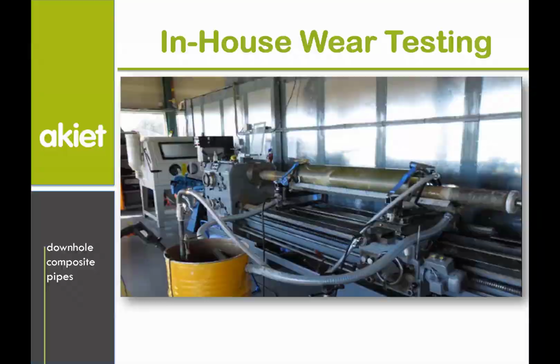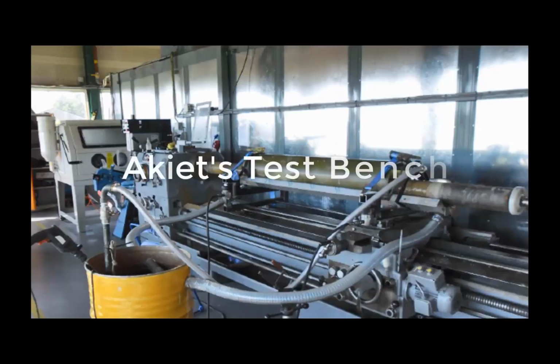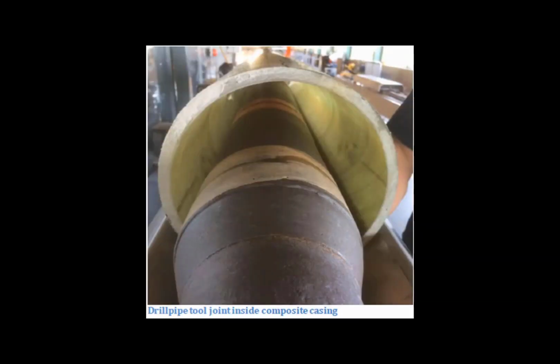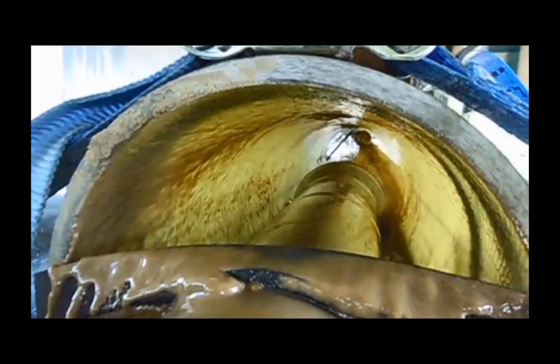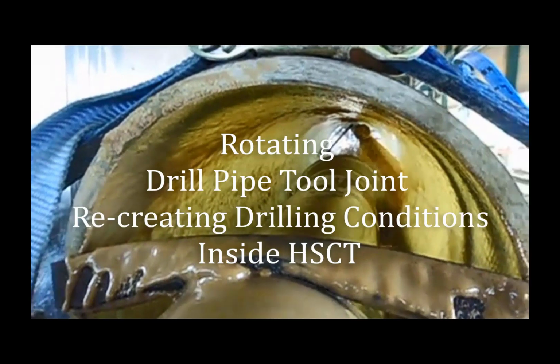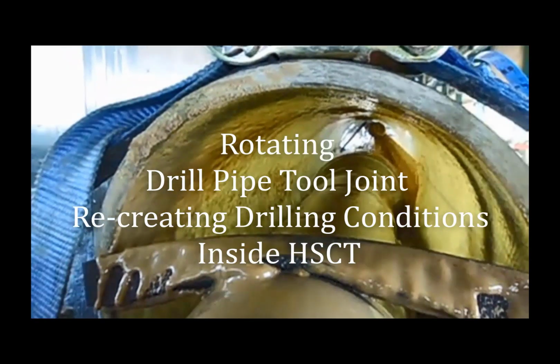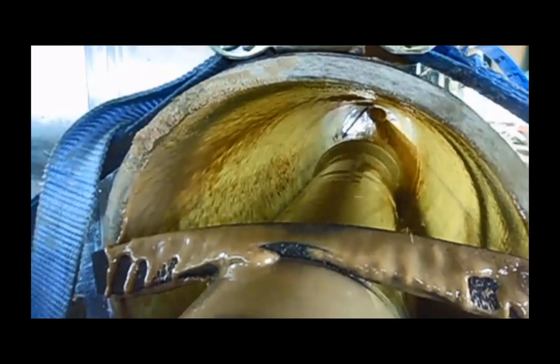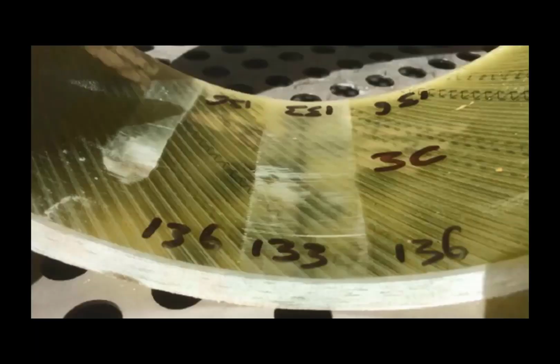So on this particular test bench, what we do is we test for wear. What happens if you install a casing and then you drill through it, and you get wear of the casing from the drill pipe being rotated? Well, what we saw is that there is hardly any discernible wear after hours and hours of drill simulation.